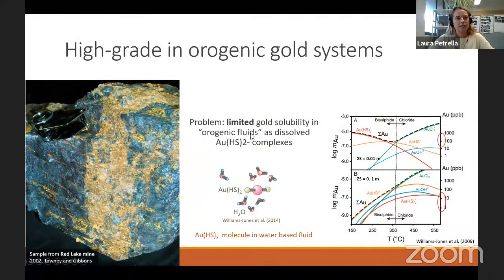One of the characteristics of orogenic gold mineralization is that it can produce extremely rich gold veins. This is an example from the Red Lake mine in Canada, where you see this relatively narrow vein that is highly concentrated in gold. This type of mineralization, which is highly localized and very, very high grade, is difficult to explain with gold transport as an aqueous species, because these species have limited solubility or maximum concentration in hydrothermal solution.